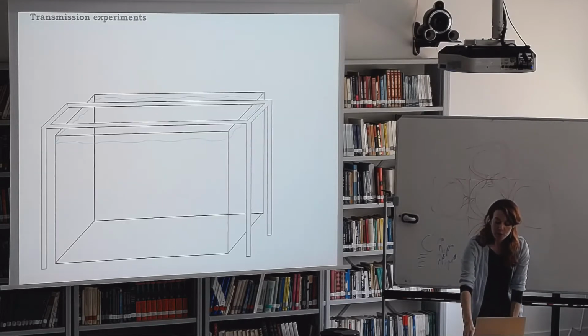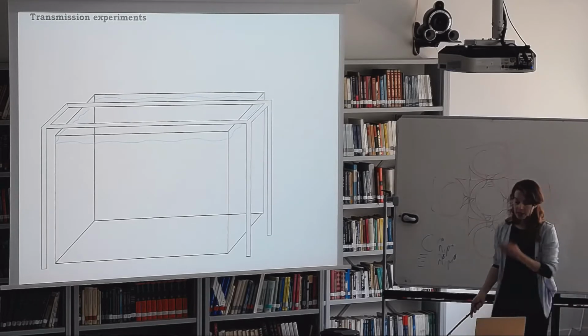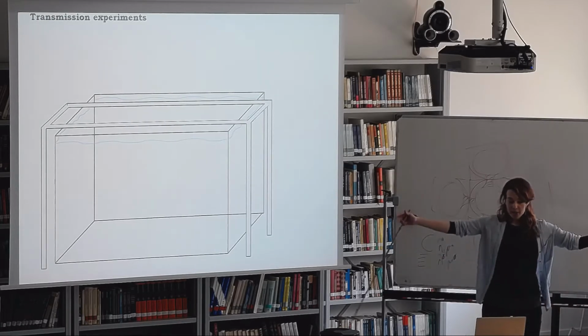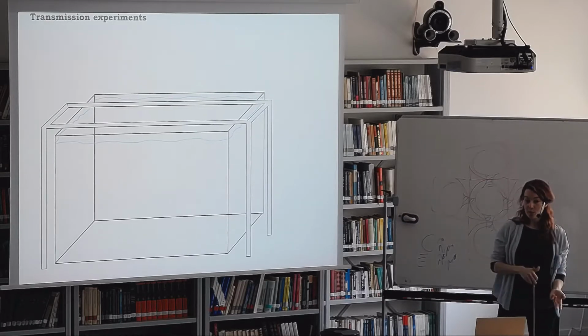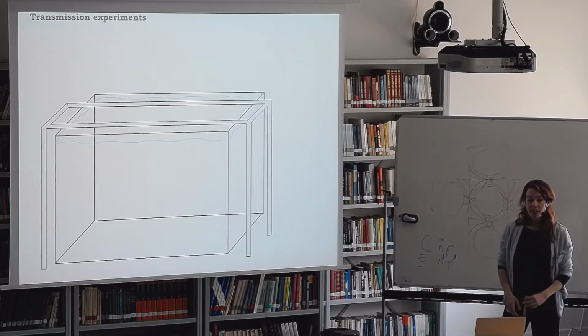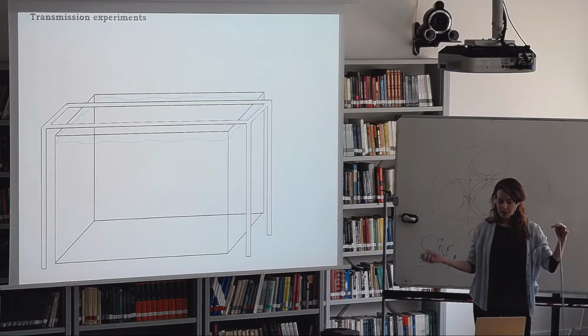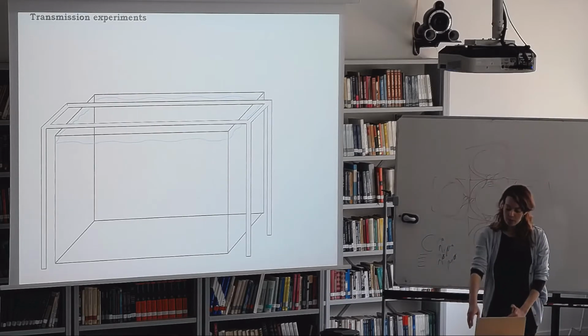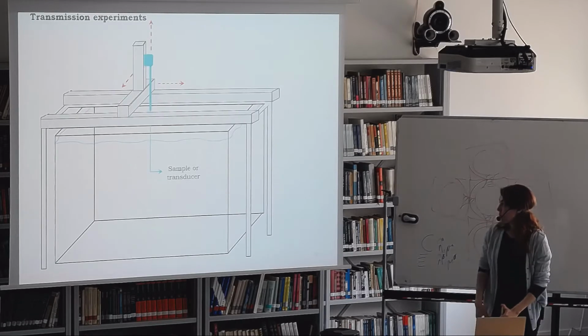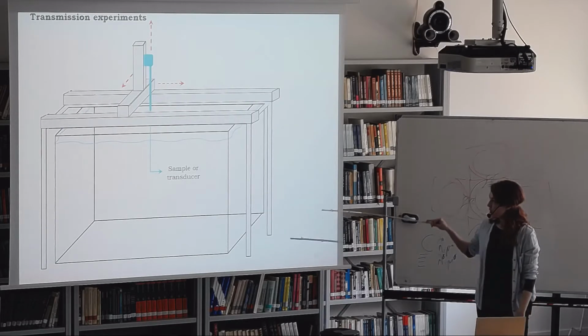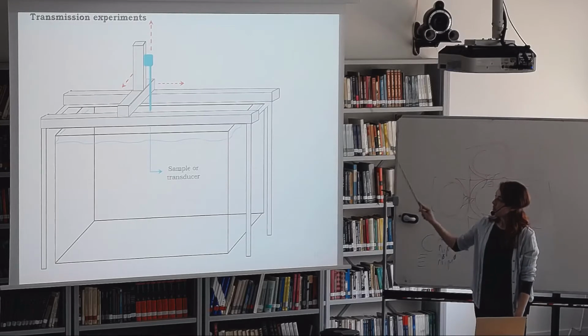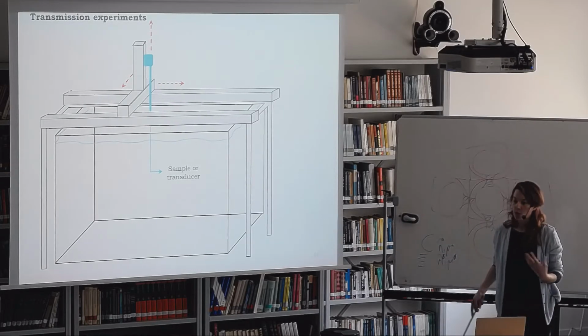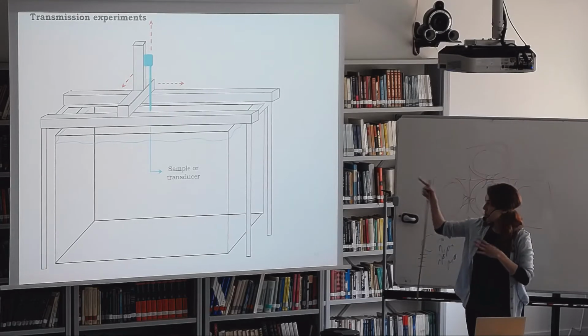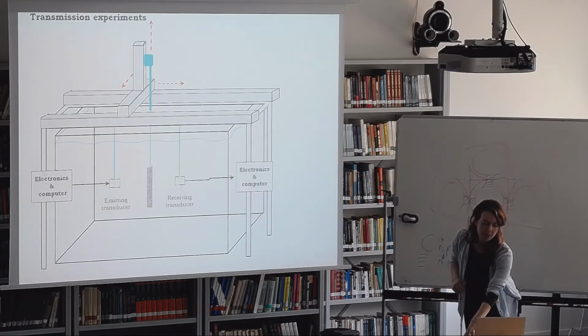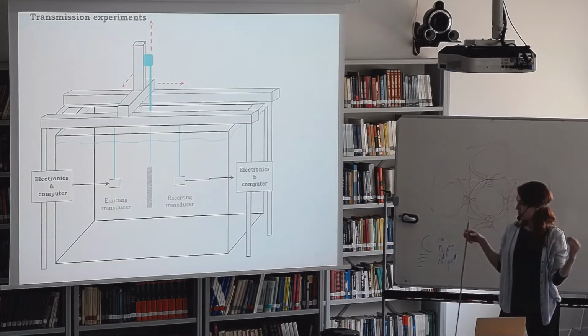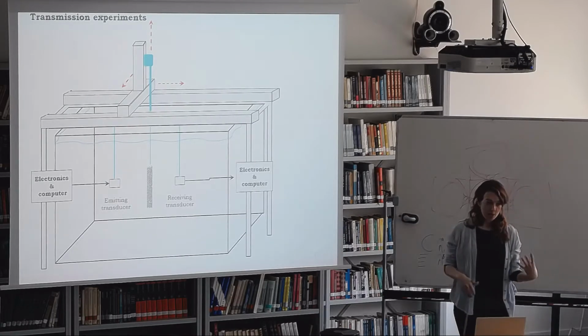So to do this, we want to be able to move things around a little bit. The experimental setup is performed in large water tanks, partly because sound experiences almost no loss in water, and it couples very nicely between the water, the ultrasonic emitters and detectors, and the metal sample. So I have these big tanks. To be able to move things around inside them, we mount motorized stages on top, and then from these we just suspend a sample or transducers. So we can move them in all three directions if we like. Then we also suspend, of course, an emitter and receptor on either side of the sample to make transmission measurements.